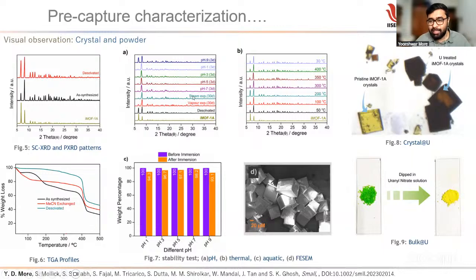So what we did, we exposed this MOF to several harsh conditions like from pH 1 for 3 days to pH 9, which is highly alkaline, as well as we did a steam exposure, like hot vapor exposure for 30 days, as well as a vapor exposure for 30 days, and then we realized the MOF is stable down to pH 1. It degrades below pH 1, but in real time we are not going to have pH 1. It will be close to the neutral pH.